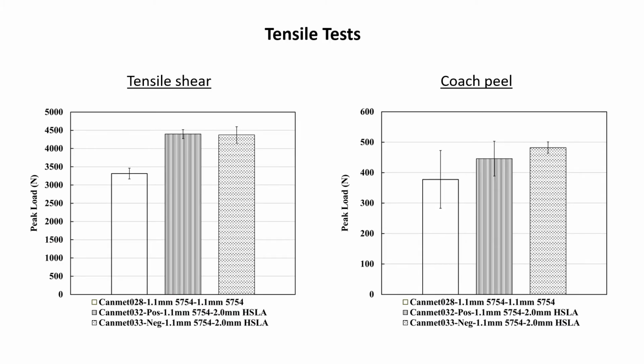Let's see the maximum tensile loads. Here are the maximum tensile loads of tensile shear and coach peel specimens with acceptable tensile peak loads. In addition, the aluminum to steel resistance spot welds have greater average maximum tensile loads than the aluminum resistance spot welds. This is due in part to the larger aluminum nugget diameters that develop in aluminum to steel welds as compared to the smaller aluminum resistance spot weld nugget diameters.